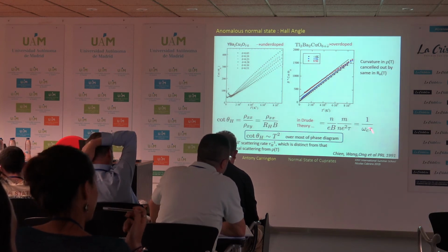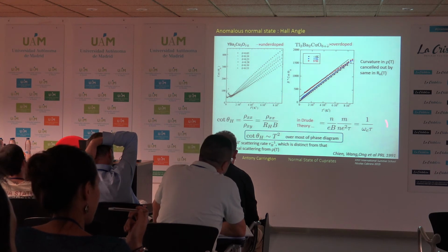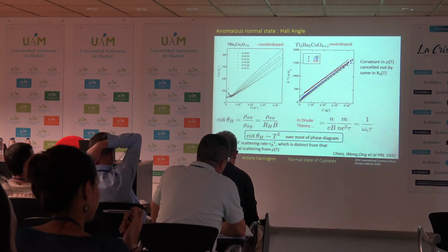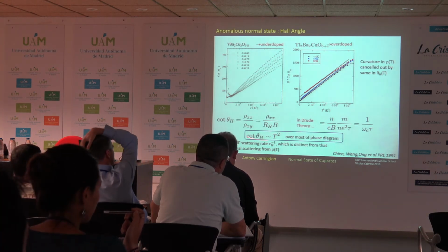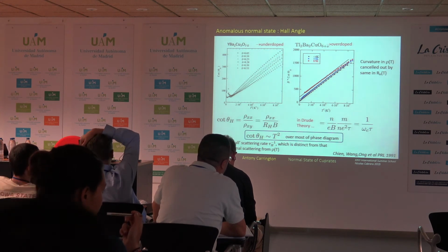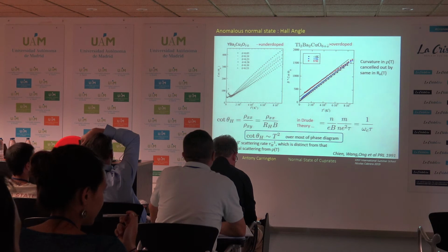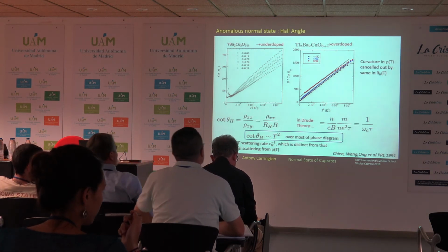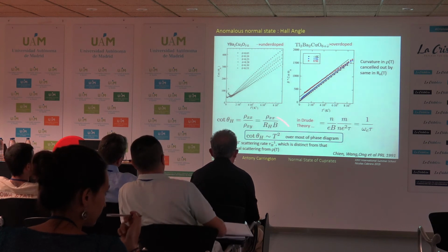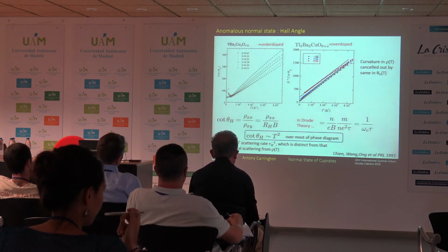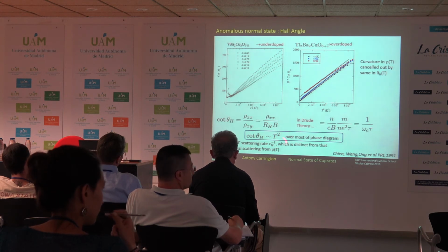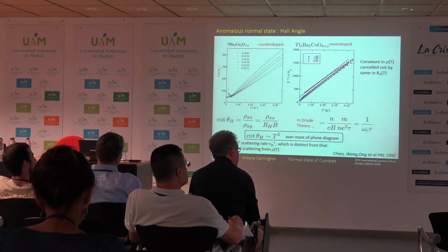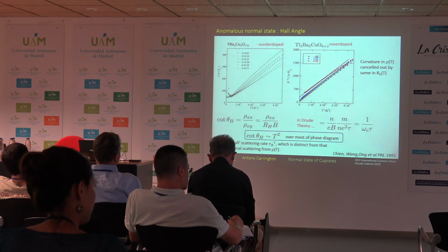So taking omega c out of this, should be telling you just the Hall scattering rate. And what the experiment seems to tell you is that this varies like T squared over most of the phase diagram. Okay, so irrespective of what's happening to the longitudinal scattering rate, the Hall scattering rate varies like T squared. So what that seems to imply is that there's a different type of scattering which turns up in measurements of the Hall effect, which is different to what occurs in the longitudinal one.